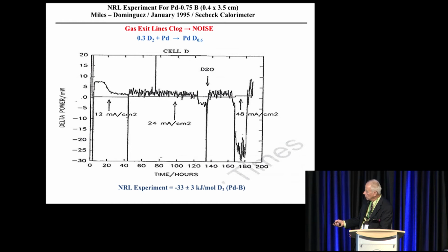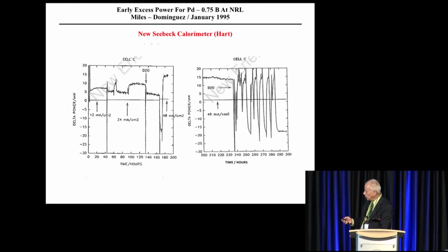It's still above 0. And if you go to another cell, they ran 2 cells simultaneously. If you go to this other cell, you see the loading, but it doesn't go away. Even when it should have been completely loaded, the excess power continues. And it even goes up higher than you'd expect from loading and continues on. And they even boosted the current up. It's still a fairly low current, but then they got excess power up to here, to 15 milliwatts. And then the gas clogging of the lines sets in, and you have that.